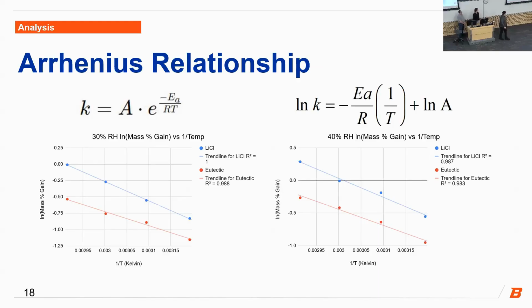All right, so as Jacob mentioned previously, we're utilizing the Arrhenius equation for our salts, specifically for lithium chloride and our eutectic. However, how do we know if the Arrhenius equation is viable for our salts? So what we did is we rearranged the equation, and then we plotted out the inverse of temperature versus the natural log of K, K being our mass percent gain. And if the plot is linear, then we know that it is viable, in which case it is very linear.